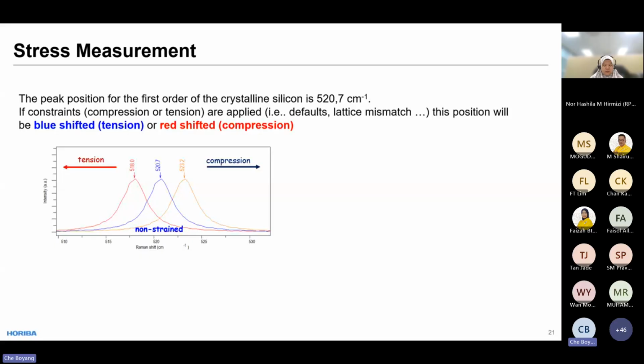And the next example on the semiconductor is on the stress strain measurement. For the silicon peak, we are supposed to see this peak at 520.7. However, if the silicon material is under compression, this peak will be shifted to the right-hand side. If this peak is under tension, then this peak will be shifted to the left-hand side. So by studying the peak shift, we are able to get the local stress strain information of this silicon sample.